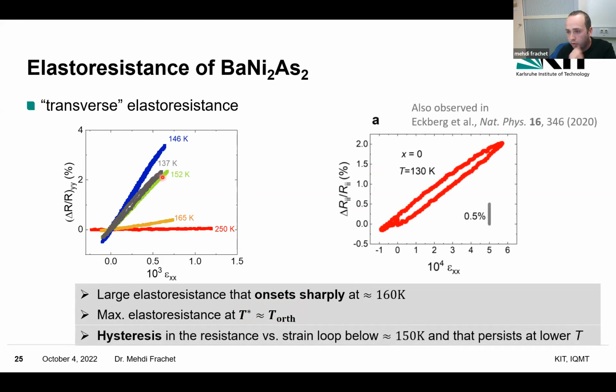One thing I would like to mention is that there is a hysteresis in the resistance versus strain sweeps. This is best seen at 130 Kelvin, what you can see on the right side. This hysteresis was also observed in the strontium-doped sample and in the undoped sample as well. This hysteresis onsets below 150 Kelvin approximately, and it persists down to the lowest temperature that we have measured. I will come back to this hysteresis in more detail when we investigate the doped samples.